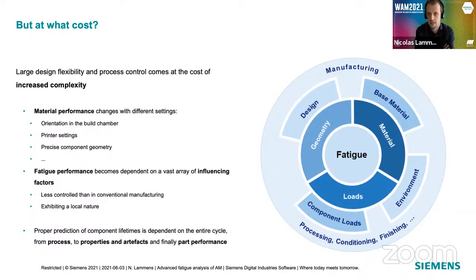But when you step into the domain of additive manufacturing, you have to start taking into account the manufacturing process itself. And because of that single extra layer that you have to account for, all these parameters or all these domains start to interact with each other. And that means that, for example, the material performance that we have here becomes dependent on the manufacturing process itself, but it also becomes dependent on how you orient your component within the build chamber, on the printer settings that you used, and it becomes dependent on the geometry that you have. Because if you have thin-walled features, for example, the local material properties will differ from the bulk material. And that's an important one to know.